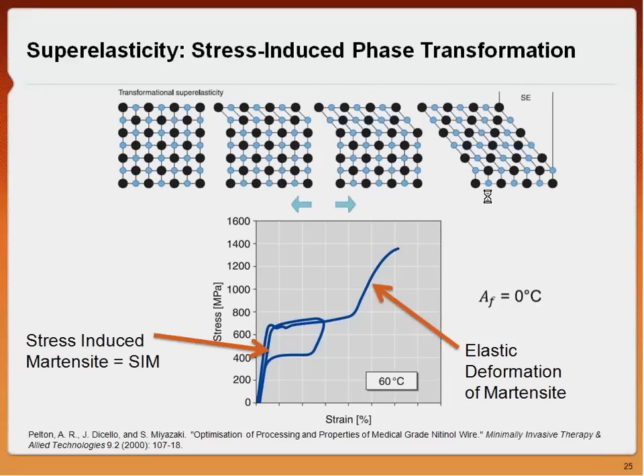So this occurs, and I want you to understand that this occurs, through the same mechanisms that shape memory occurs through. The only difference is it's an applied stress at a warm temperature. So what happens is you start with the ordered austenite cubic structure over here, with every large black atom being nickel and every small blue atom being titanium. And as soon as you're applying the stress, you have slight shearing movements. And what's happening is you are stress-inducing martensite in the material.